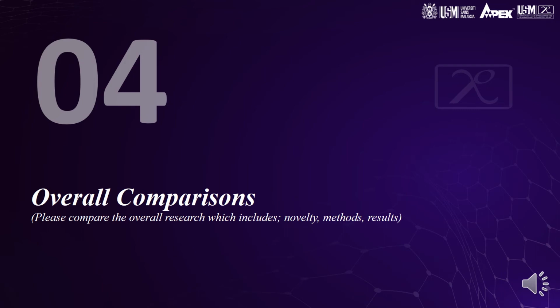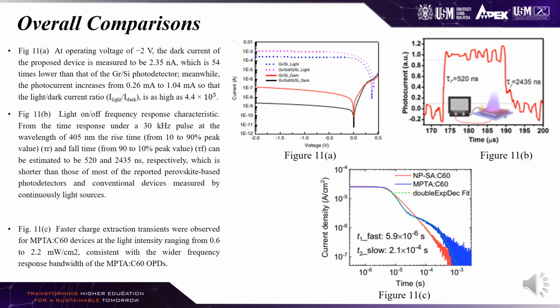This is the overall comparison. Figure 11a shows at operating voltage of negative 2 volt, the dark current of the proposed device is measured to be 2.35 nanoampere, which is 54 times lower than that of the graphene silicon photodetector. Meanwhile, the photocurrent increased from 0.26 milliampere to 1.04 milliampere, so that the light to dark current ratio is as high as 4.4 times 10 power 5.